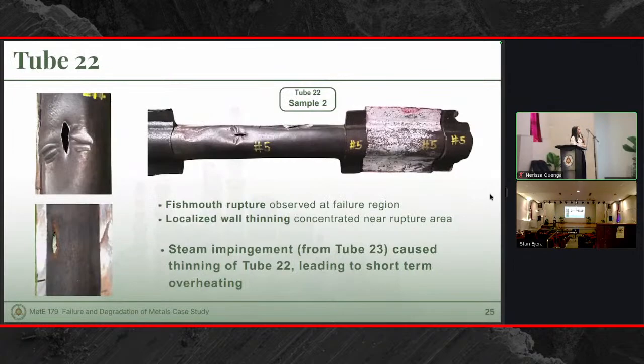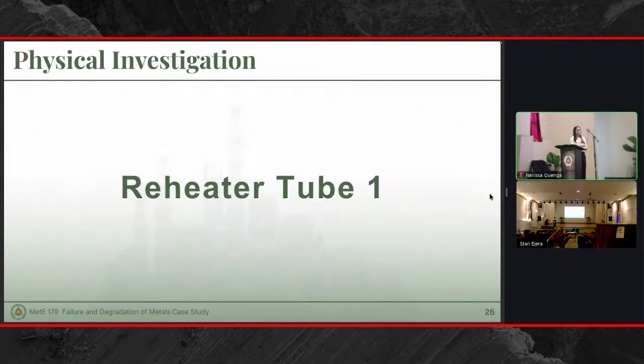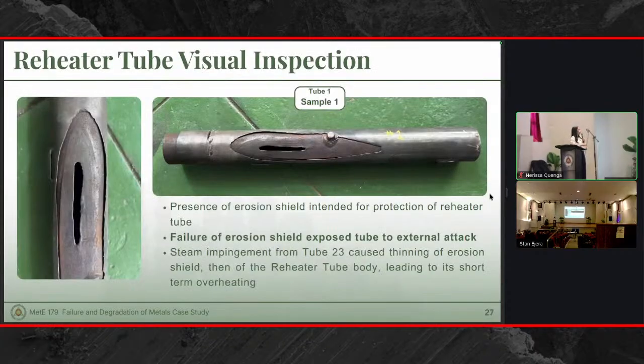So from that, we conclude that the steam impingement from tube 23 caused the thinning of tube 22, leading to short-term overheating. Moving on to reheater tube 1, from visual inspection alone, we can already see that the failure started from external forces, since the erosion shield, which is supposed to protect the reheater tube 1, experienced significant damage, even more significant than that of reheater tube 1. It has significant thinning and the rupture is observed.